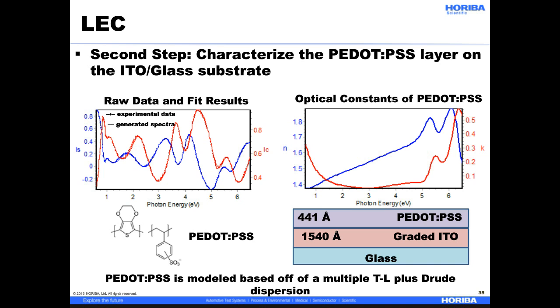On the right are the optical constants of the PEDOT-PSS layer. So PEDOT-PSS here is modeled off of a multiple Tauc-Lorentz plus a Drude dispersion. Again, you can try, instead of multiple Tauc-Lorentz, multiple new amorphous plus a Drude.